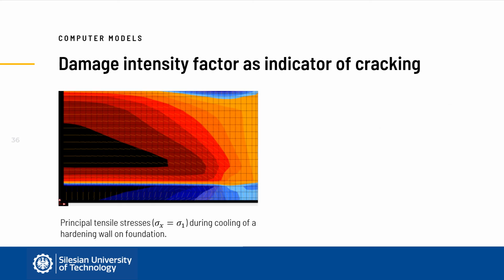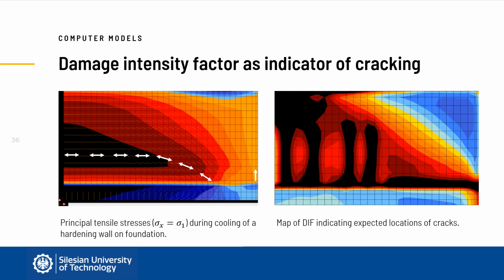In the slide you can see a map of stresses in a half of a reinforced concrete wall, in which a contraction caused by shrinkage is restrained by a foundation. In such a case, the horizontal stress is equivalent with one of the principal stresses and causes tension in the wall and compression in the foundation. The following map of damage intensity shows the level of stress with respect to the tensile capacity of concrete.